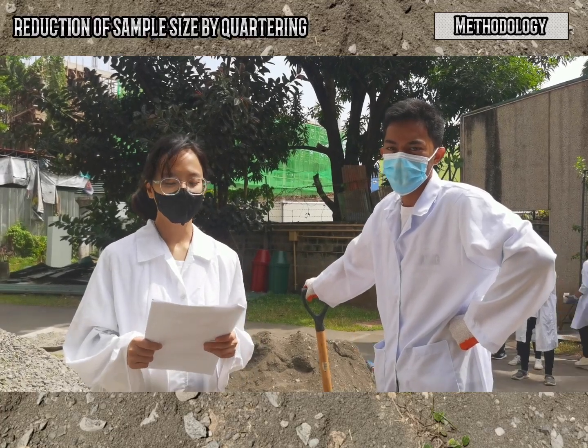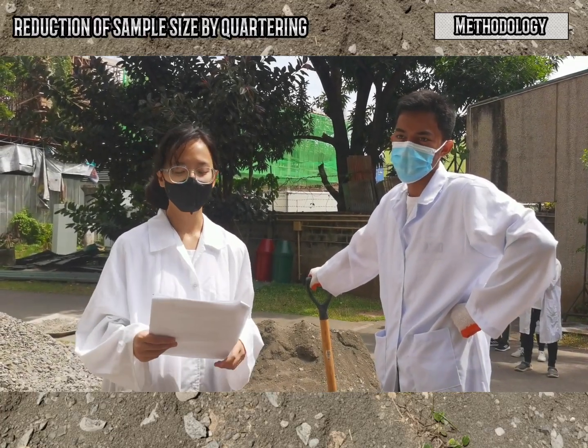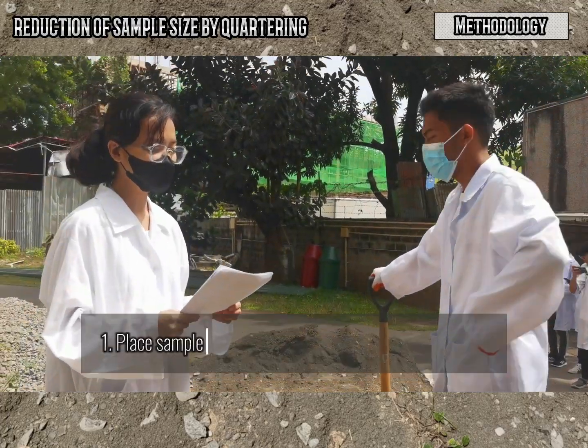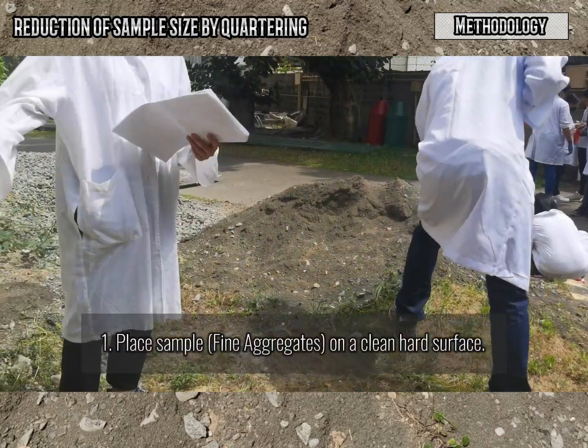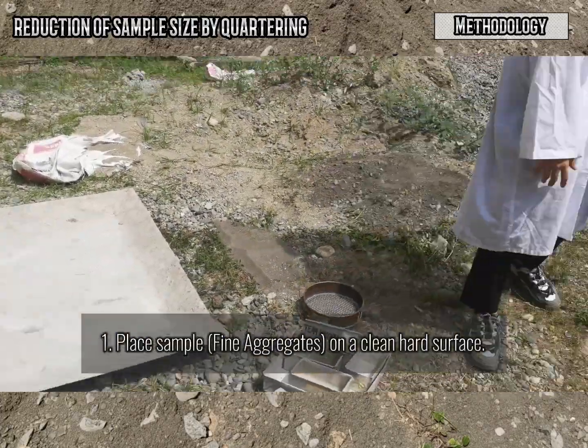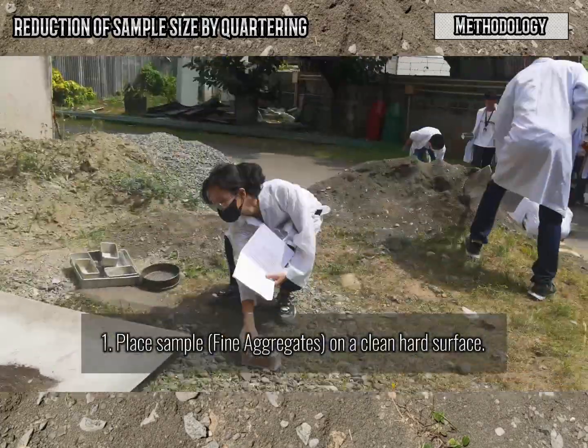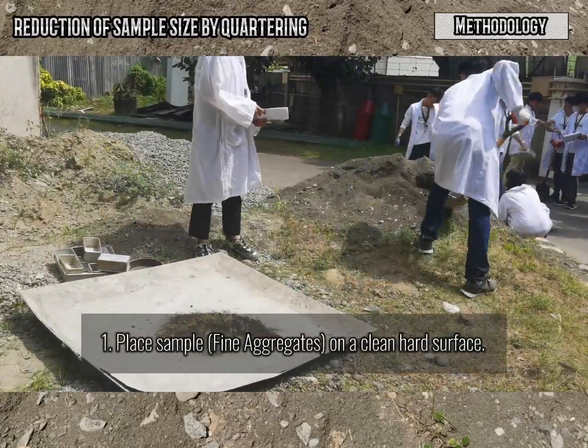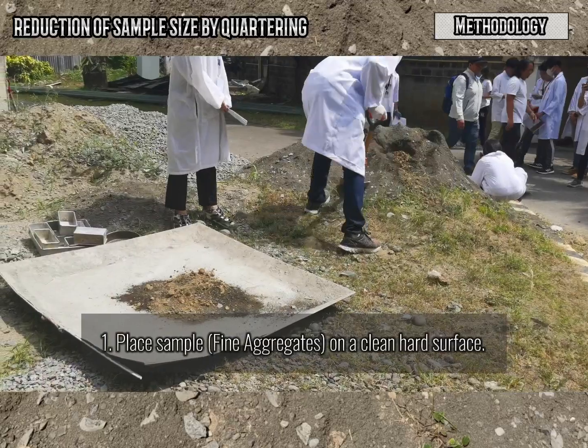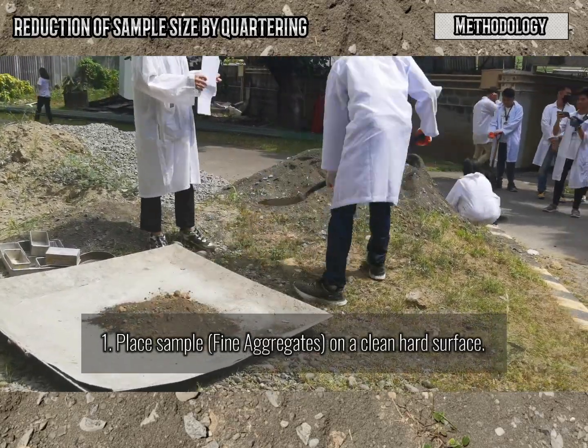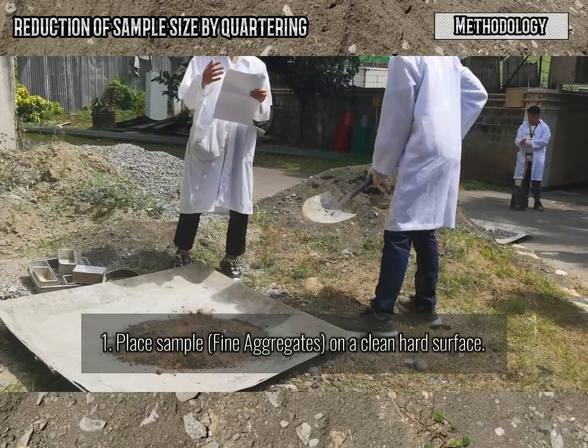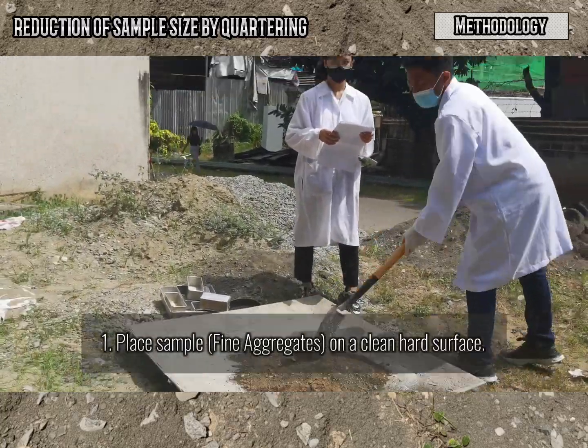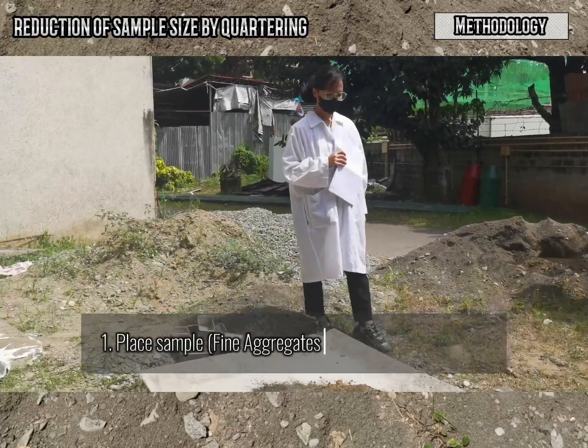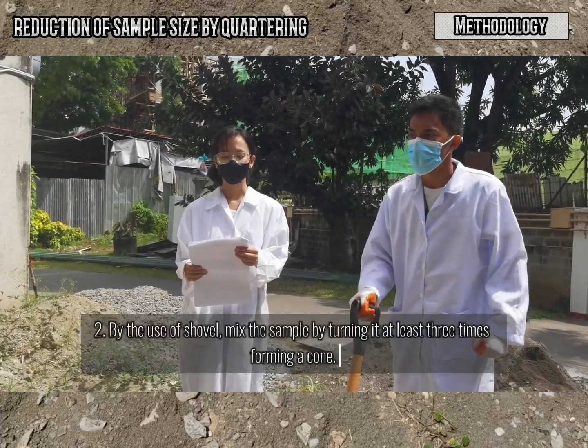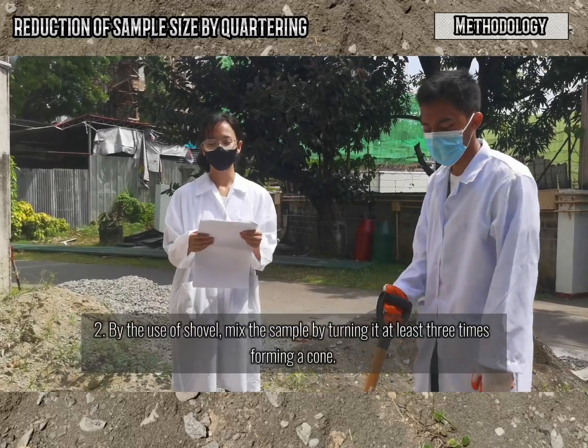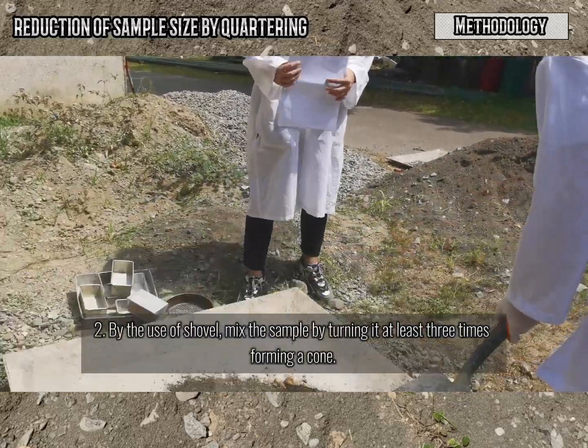And now we will start to reduce the sample size by using the quartering method. First, place the sample of fine aggregates on a clean flat surface. Next step is, by the use of a shovel, mix the sample by turning it at least 3 times, forming a cone.